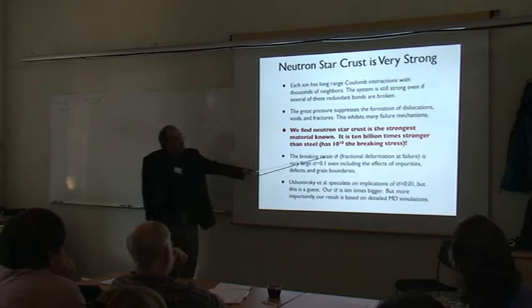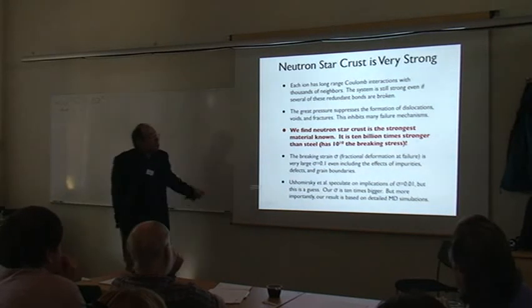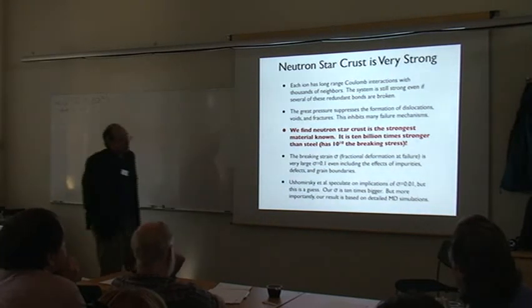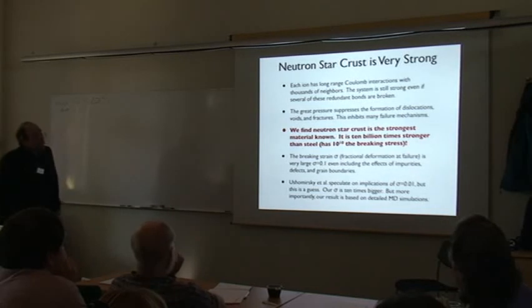The breaking strain, the fractional deformation at failure, is very large, around 10%, even when you include the effects of impurities, defects, and grain boundaries.